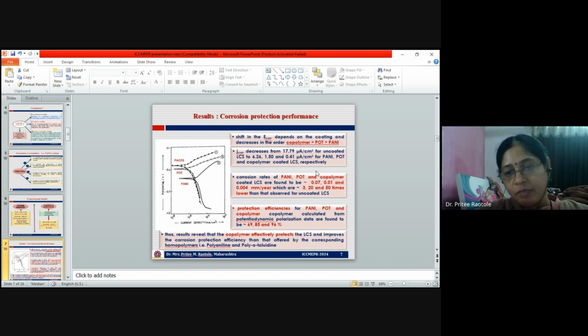We have synthesized the polyaniline, poly-o-toluidine and copolymer, that is the combination of poly-o-toluidine and polyaniline in the ratio of 50-50 concentration. So that is treated as PaOT5, and compared the potentiodynamic polarization measurement results of these three types of coatings, which reveal that the copolymer effectively protects the LCS and improves the corrosion protection efficiency than that offered by the corresponding homopolymers. The homopolymers are polyaniline and poly-o-toluidine.